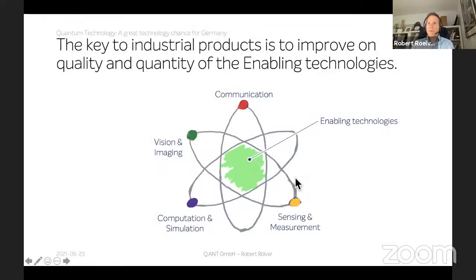And in between, to bridge this gap, we need something that we call enabling technologies, which requires a lot of engineering. So, for example, shown in the first talk by Mathieu, this diamond growth is really an enabling technology, which took about, I think, 10 years for Element Six to go from first CVD nitrogen doped samples to this real high quality diamonds with NV concentration in the ppb range, or with T2 times of a millisecond.